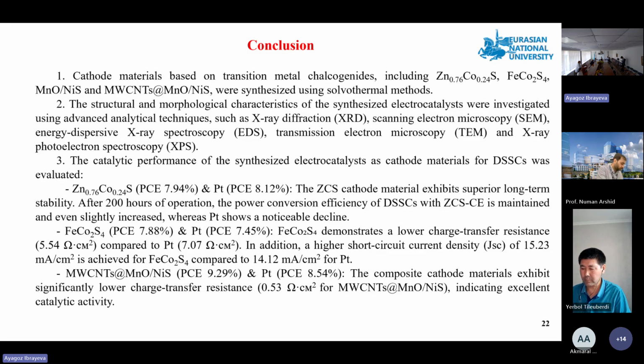Iron cobalt S4 nanowires demonstrate a low charge transfer resistance of 5.54 compared to platinum 7.07. In addition, a higher short circuit current density of 15.23 milliamperes per square centimeter is achieved for iron cobalt S4 compared to 14.12 milliamperes per square centimeter for platinum.